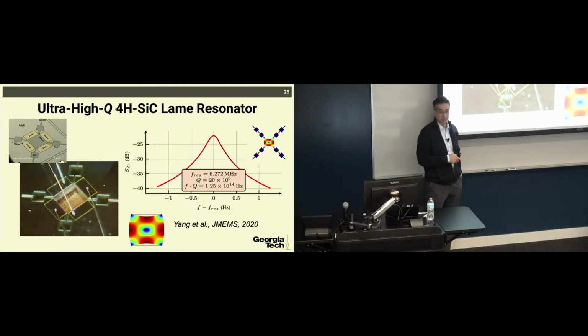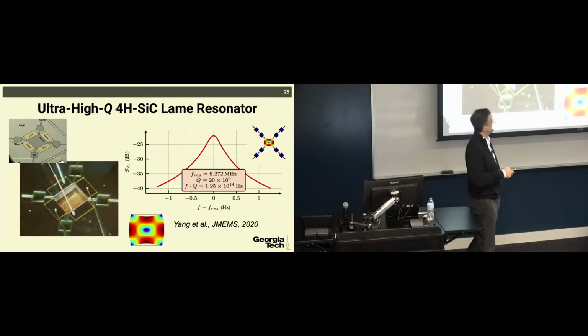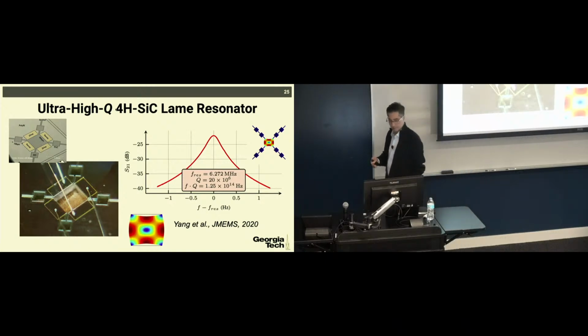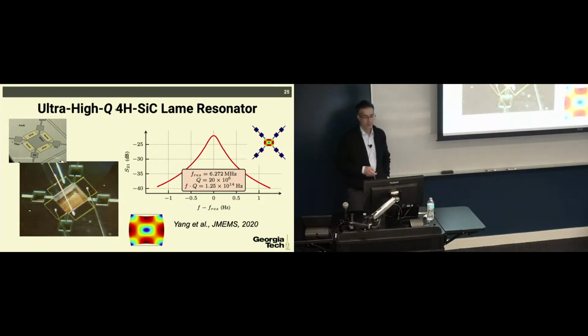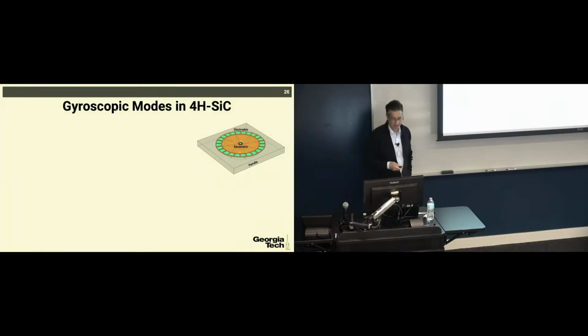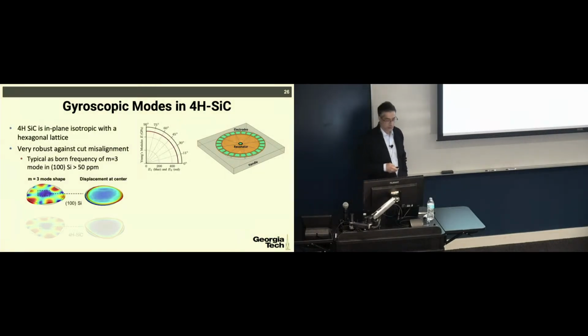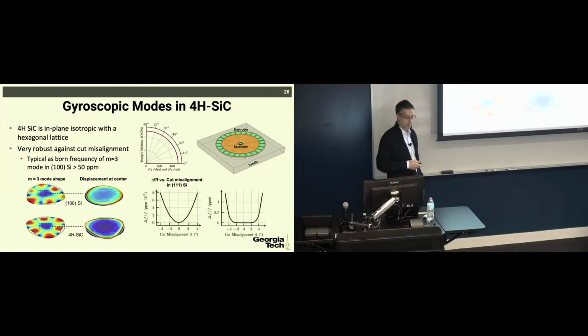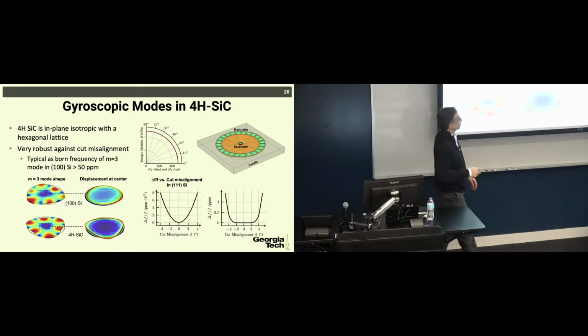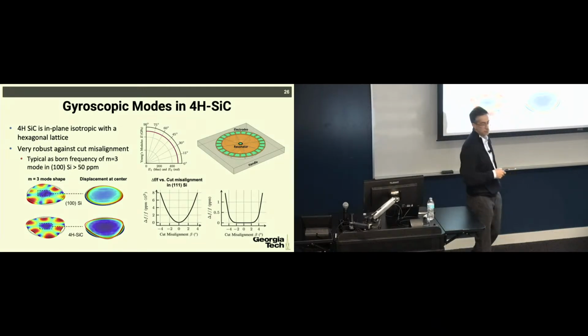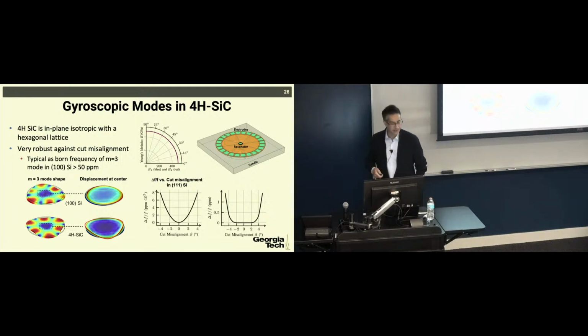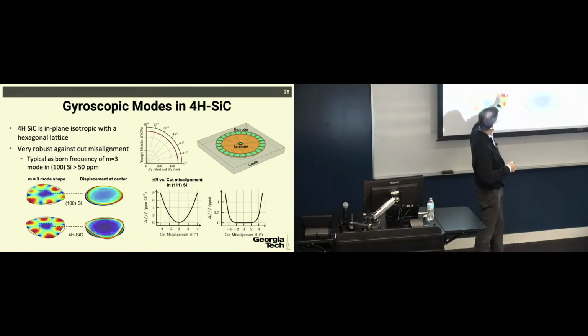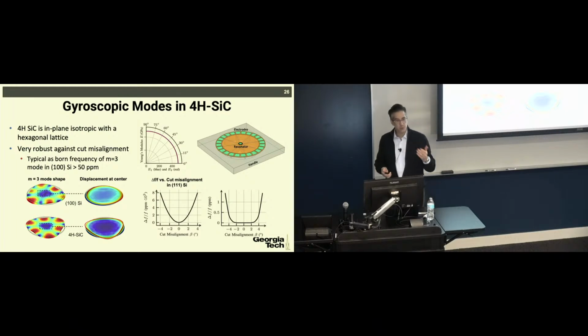And we actually expected it. We wanted to get even to higher Q factors. So this is already 5 times higher than silicon can get to, even in a suspended structure. But we have another 5x to go before we are limited by the Akhiezer loss of silicon carbide. Now, we were also very much interested in using silicon carbide for a gyroscope application. And this is where silicon carbide shines, which is in the 4H polytype, the hexagonal lattice will cause the split between the gyroscopic modes to be extremely small as a function of process variation, which is a huge difference compared to silicon.